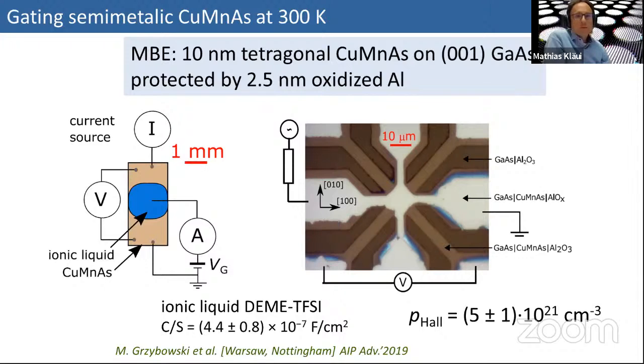It would be at lower temperature because of the ordering temperature of the copper manganese. Yeah, we did everything at room temperature, and of course, ionic liquid is a very nice capacitor. You can get a very large capacitance, but only when it's liquid. By definition, people cool down, and it's very tedious because if you want to change voltage, you have to heat up again and so on. Yeah, I understand. But it works perfectly at room temperature. It is not so good at lower temperature.